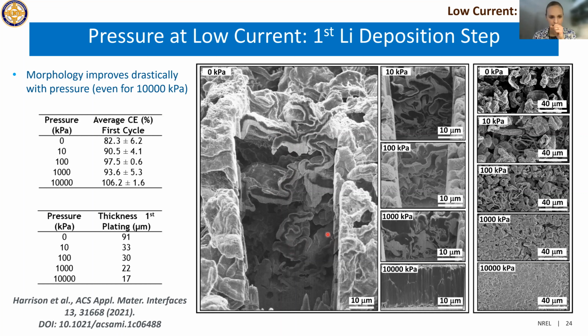But you can see, from the top down images of these electrodes, the porosity of the lithium metal goes down with increased pressure. You can also see that in the cross-sectional imaging here. And then we have the thickness that we measured from these electrodes depending on the pressure. So at 0 kPa, it was almost 90 microns thick, whereas at 10,000, it got all the way down to 17 microns thick. And you can see there are very, very small pores in here, and it's mostly just very dense lithium deposits in very large grains.